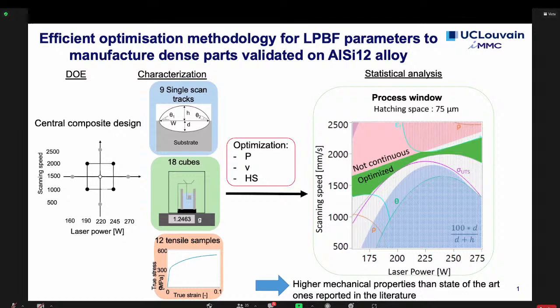So here we think we minimize the manufacturing cost, because to manufacture just one single track, it's really not a lot of material. Then you have to manufacture 18 cubes and 12 tensile specimens, but you can have really strong conclusions after that, and you're sure of the influence on the mechanical properties. So with the design of experiments, we could really minimize the number of trials that we have to do to reach this conclusion. If we minimize this number of trials more, we could not get conclusions that strong.